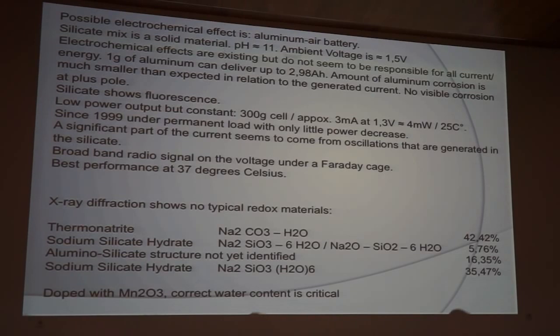The X-ray diffraction shows thermonatrite, which is rather a rare form of sodium carbonate, then differing sodium silicate hydrates, silicate oxide, and an alumino silicate structure that could not yet be identified. This whole thing is doped with a ferromagnetic isolator of manganese oxide.